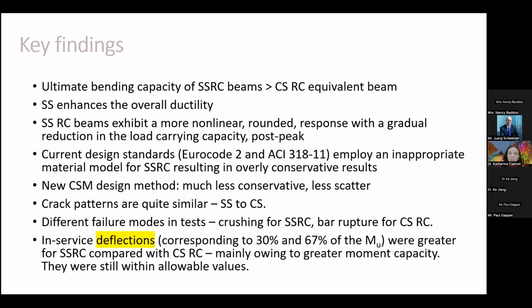So just a summary of some of the key findings from our research studies. Generally, the capacity is higher for stainless steel reinforced concrete members, with better ductility, a more non-linear, rounded, gradual response compared with carbon steel reinforced concrete. Current design expressions in the Eurocode are overly conservative for stainless steel reinforced concrete, and some of our newly developed methods provide a less conservative, less scattered set of data. Cracking was really similar. Between the carbon steel and the stainless steel beams, the crack patterns and the developments of cracks and the deflections at which they developed were shown to be really similar.